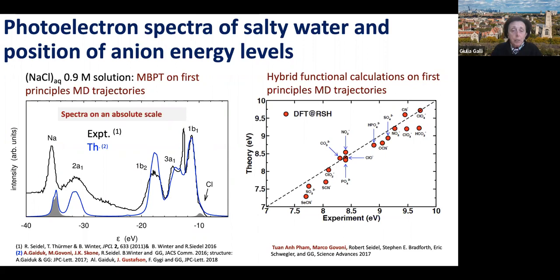What I'm showing here is a photoelectron spectra, shown on an absolute scale. This is actually our important accomplishment. These spectra are not shifted. They are computed on an absolute scale, and they are computed on an absolute scale because we could actually do a simulation also of the surface of water. And they are compared with experiment. And there is a salt in water because also experimentally there are often salts. And the agreement with the experiment, and the experiments were done by Bernd Winter and Robert Seidel in Berlin, is actually very good. And to get this kind of agreement, we had to do simulation with the hybrid functional. And then on top of this, we did GW calculations.